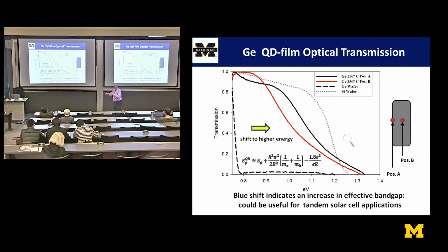This is not just one particle, it's the average of a whole macroscopic number of nanoparticles deposited as a film, with an optical absorption curve, or transmission in this case, that is intermediate between germanium here and silicon here. This could be quite useful for solar, tandem solar cell applications, where you make an additional layer in the photovoltaic material to capture infrared, which is where the majority of the solar spectrum occurs.